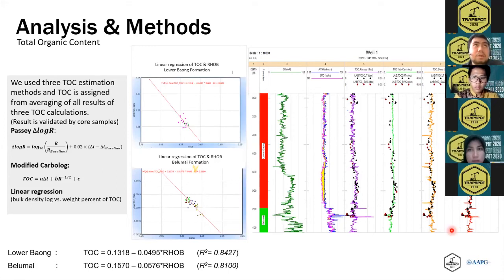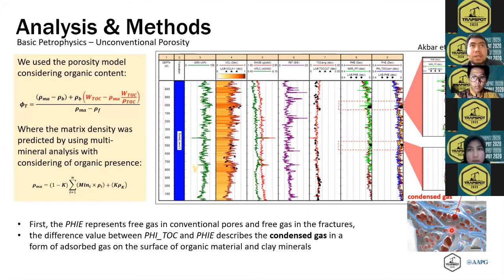And after that, we calculated the porosity. To calculate the porosity, normally you use this equation without considering the TOC. This is the total porosity that we usually calculate. However, for the matrix density, it is really recommended to use the multi-mineral analysis, and the grain density from the multi-mineral analysis should be taken into consideration to calculate the porosity, but also the organic content in weight percent of the TOC should be calculated as well, in order to define the porosity considering the organic.